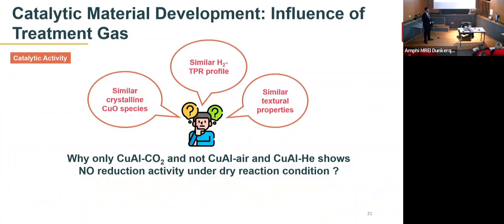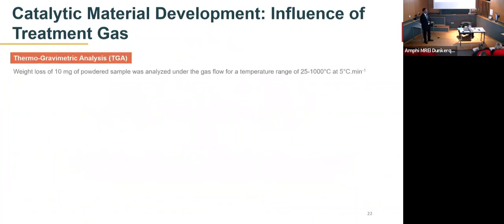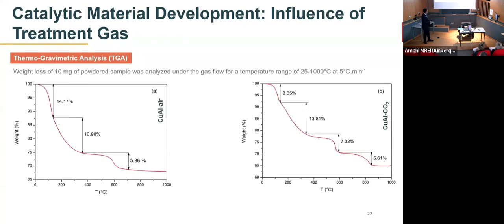So in order to further investigate this question, we went with a characterization technique called TGA or thermogravimetric analysis to see what happens during the treatment process. So in this case, we pass the desired gas through the sample for a temperature range between 25 degrees Celsius to 1000 degrees Celsius. So here are the weight loss curves for both the samples of air and carbon dioxide treated mixed oxides.